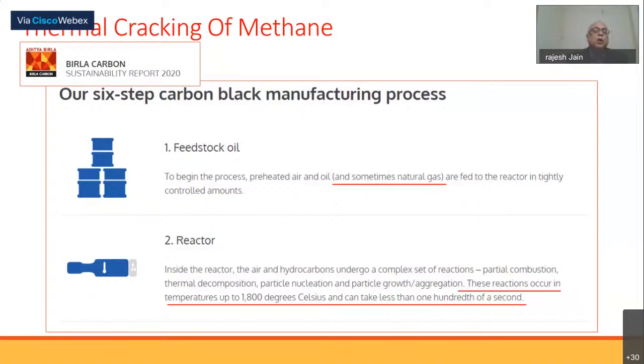It is noteworthy to mention that what the scholars are attempting has already been carried out in the industry. This website snapshot of Birla Carbon depicts their six-step carbon black manufacturing process. They're using a similar method to produce a special grade of carbon black from natural gas. The underlined portion clearly mentions something like that. Natural gas is fed into the reactor in tightly controlled amounts. These reactions occur at temperatures up to 1800 degrees Celsius and can take less than a hundredth of a second. It's the same thing as what the scholars are attempting. Next one, Gautam, please.